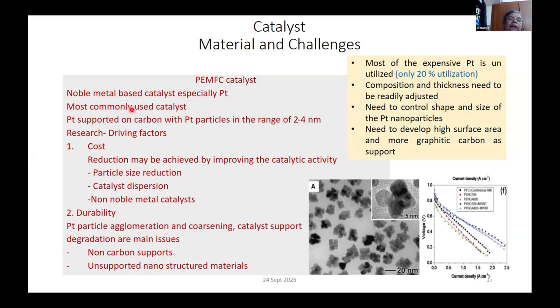Then this platinum, you can use pure platinum as particles, what is called platinum black, or you can use it supported on carbon. When you support it on carbon, the platinum particles are in the range of 2 to 4 nanometers, and the chances of them coalescing back during the reaction are very low. So most of the research is on platinum supported on carbon.